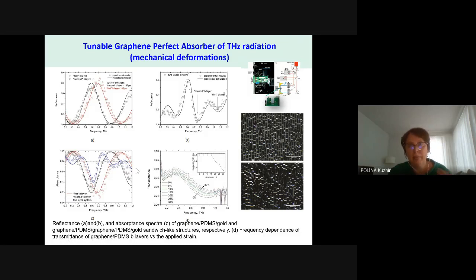Since we're dealing with quite high frequencies, we don't need to worry much about what happens if graphene breaks during stretching of the polymer. These small pieces of graphene will feel each other electromagnetically, and we demonstrate both theoretically and experimentally that up to 30% deformation of the polymer, there's no substantial difference in the conductivity of graphene. So we could stretch and de-stretch it many times and get the same results for tunable graphene perfect absorption.